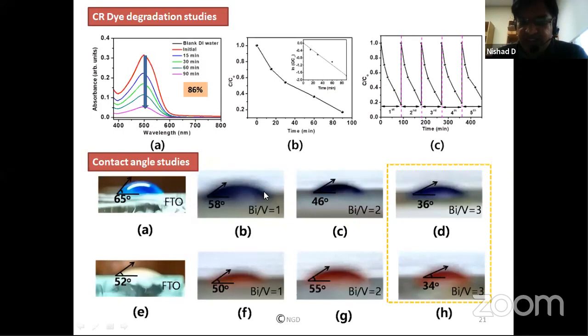And we tried to understand using the contact angle, because this actually gives us the active surface studies, understanding the contact angles, like whether it is hydrophilic or hydrophobic surfaces. So what we can see is, with respect to the Congo red dye on the bismuth vanadate structure, we can achieve a very low angle, almost like 34 to 36 degrees, which means that the dyes are highly intercalating with respect to the surfaces of the bismuth vanadate nanostructure. So this means these dyes will be degraded rather fast on these surfaces.